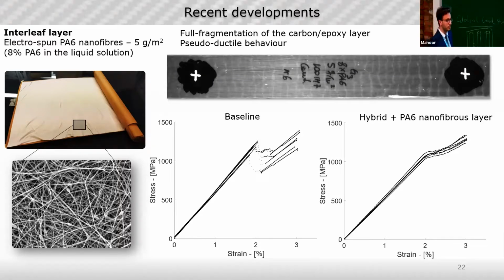They are capable of introducing crack deflection mechanisms or crack arresting mechanisms that can help us to suppress the delamination when the cracks want to propagate between the interlayer, between the carbon and the glass. And putting the layer of the nanofibers gave us a very nice transition, so very good pseudo-ductile behavior. Also, I want to highlight the practical aspect of this approach. This is not something that requires tricky treatment of the material. This nanofiber layer is like a paper towel, so it's really easy to handle, and especially if the material is made by prepregs, the stacking process, the manufacturing process, is very easy to perform.